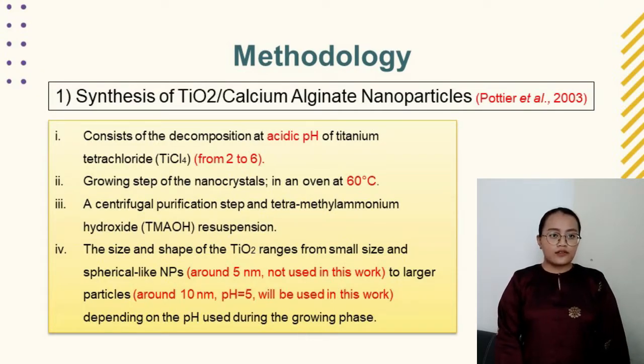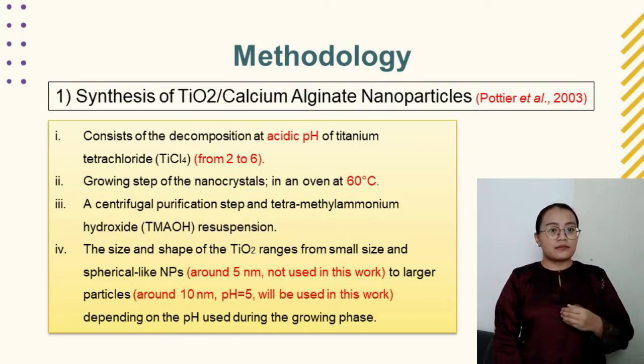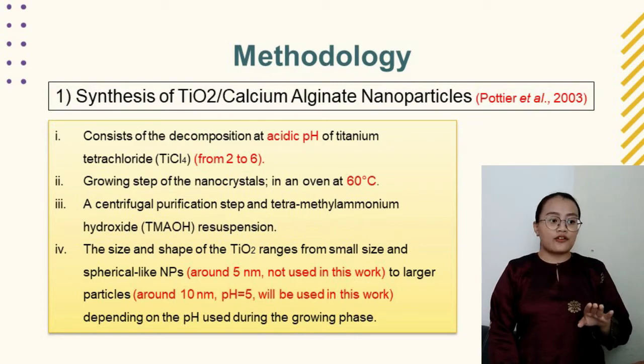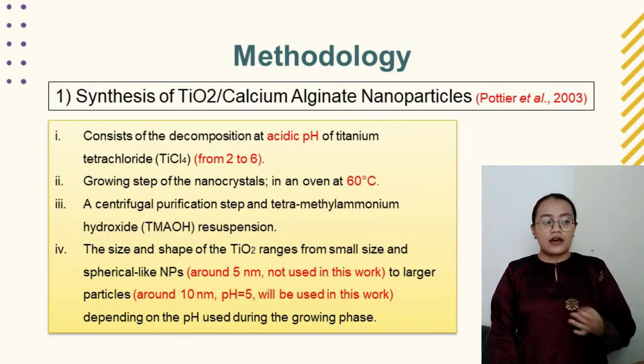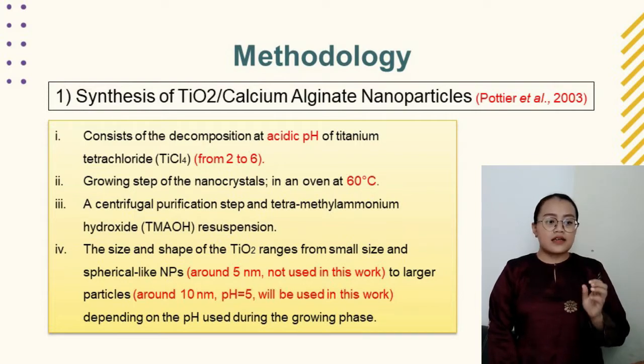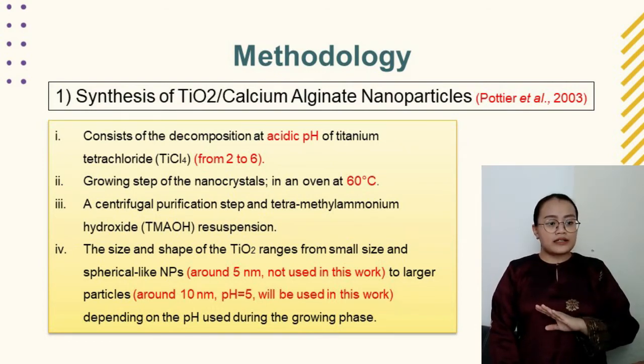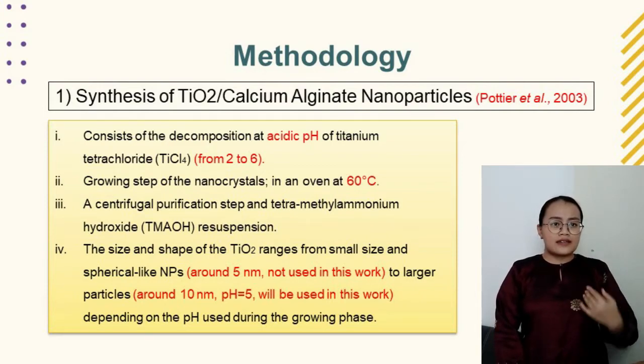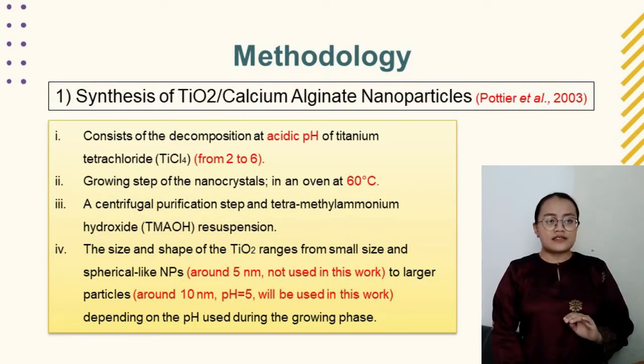The first one is the synthesis of titanium dioxide calcium alginate nanoparticles, which is taken from the previous studies by Potier et al. 2003. First, it consists of the decomposition at acidic pH of titanium tetrachloride (TiCl4), with the pH from 2 until 6. Then there is a growing step for the nanoparticles in the oven at 60 degrees Celsius. The size and shape of the titanium dioxide range from small, spherical-like nanoparticles around 5 nanometer, which are not used in this work, to larger particles around 10 nanometer at pH 5, which will be used in this work, depending on the pH used during the growing phase.